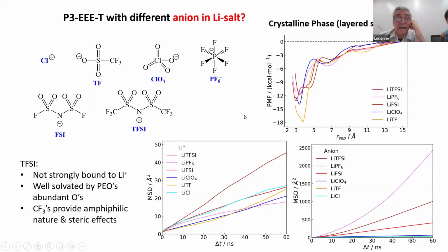Do you think there is anything related with maybe a plasticity of this local phase? Yes, exactly. That's a good point. Because of the bulkiness of these groups, it basically makes this disordered phase of the PO regions more disordered, right? So that's what I was saying. These entropic effects, counterintuitively, if you introduce more disorder, are going to affect these ion conducting regions. That's going to basically favor the mobility of the ions in there. So certainly there's an effect in there too. Really fascinating effect. It's amazing.